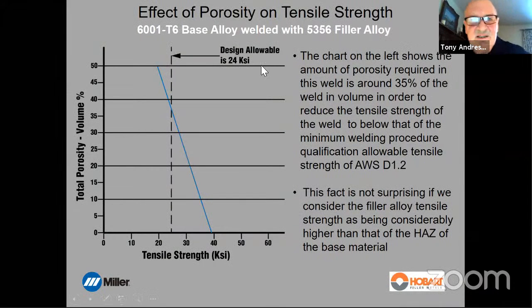This is an interesting slide, and it's a bit misleading, but it's interesting. Is porosity a really nasty discontinuity? Well, in my opinion, not really. It's a pain in the ass, and it's difficult to get rid of at times. But does it reduce the strength of the weld tremendously? No, nowhere near as much as a crack or incomplete fusion.